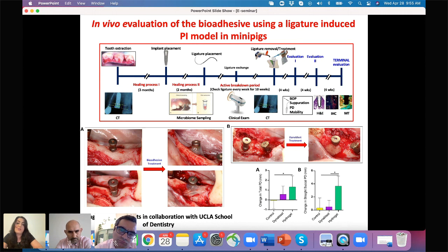Our treatment started by applying our hydrogel around the implant, and we also used a commercial bone graft to compare with. And then once we treated the pigs, we waited around 4 weeks, and during this time, we did different evaluations: H&E staining, microCT analysis, immunostaining. We also took samples for the microbiome study. And then here are some results that we obtained.